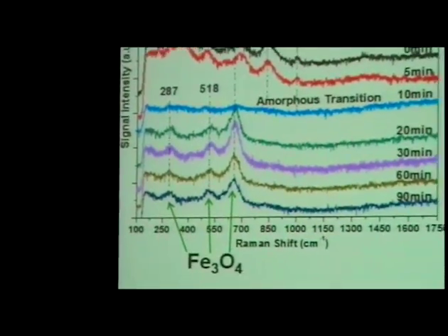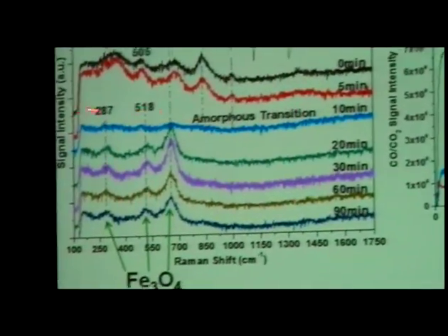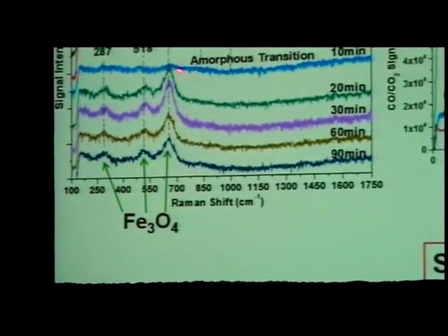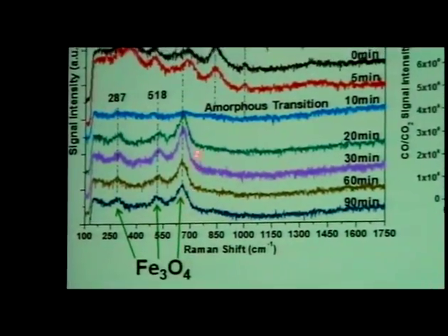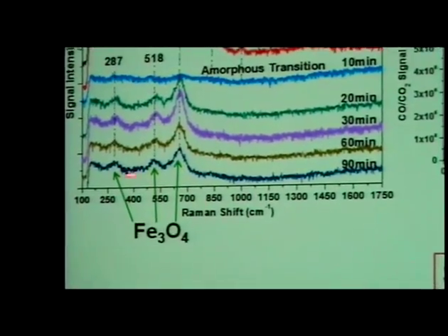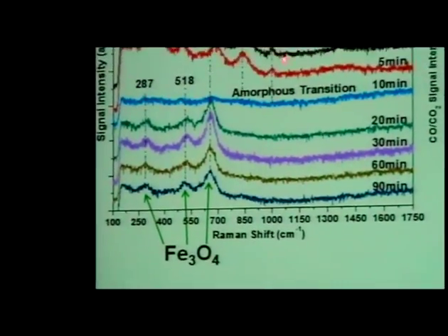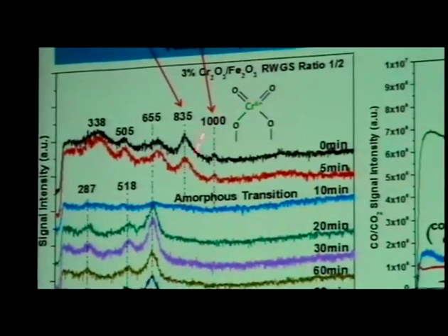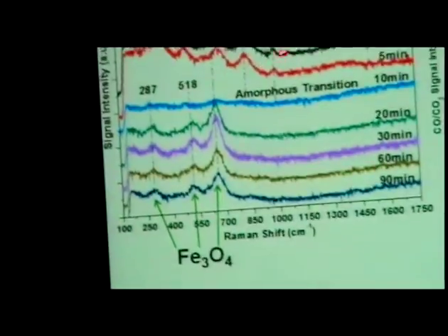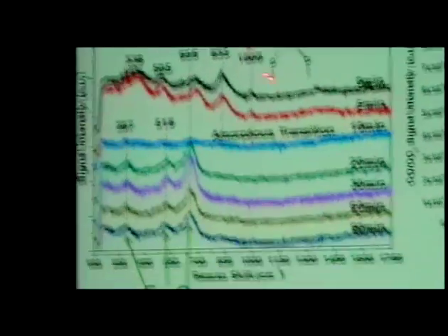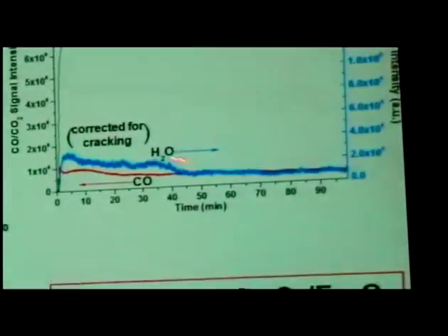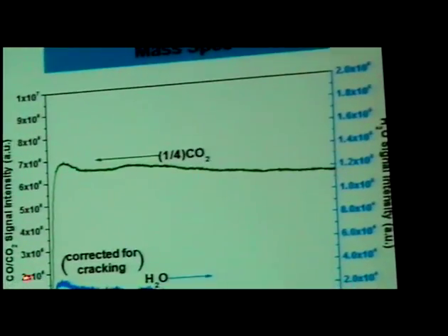Again, when you start the reaction, after a while it becomes amorphous, it's transforming, and it comes back again as Fe3O4 magnetite. Notice also during this transformation, this time we don't come back with chromium 6. We lose the chromium 6 species on the surface, their signature. Again, the water gas shift reaction is occurring during this reaction.